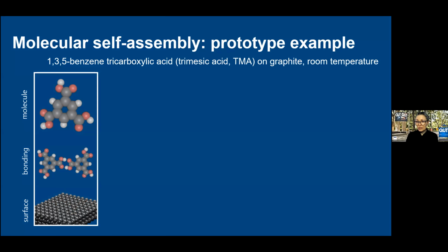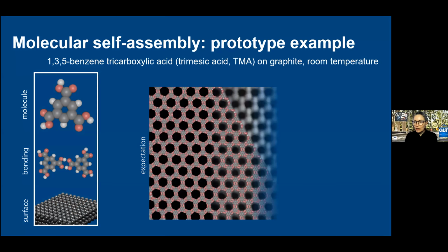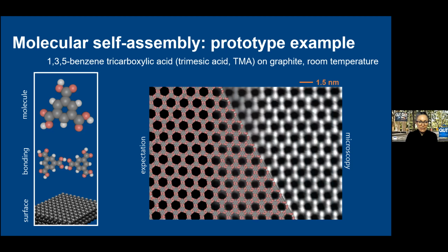This is the one I showed you before. It's called trimesic acid, or 1,3,5-benzene tricarboxylic acid, and the non-covalent interactions it undergoes are hydrogen bonding interactions through the carboxylic groups. This carboxylic dimerization has a bond energy of something like 10 kilocalories per mole per molecule. It's extremely directional. There's a very good matching here. So we can very easily predict the type of architecture that we will see out of a self-assembly of trimesic